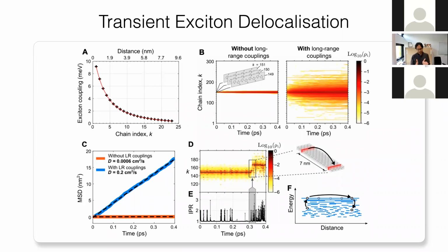What I mean by that is now we have not just the localized exciton picture in this system, but we also appreciate that there are higher lying states over here. So what that means is that when we initially excite our exciton, we form a kind of wave-like state, which is high in energy. And then that undergoes scattering and is localized. Normally in quantum mechanics, generally speaking, the path from delocalized excitation to localized is one way. Once something localizes, it doesn't really go back to the delocalized state because that's normally uphill in energy, and quite significantly uphill. But in these systems, it seems that we can actually go from the localized exciton, which would normally be doing only FRET, which would be very slow, back to delocalized excitons.